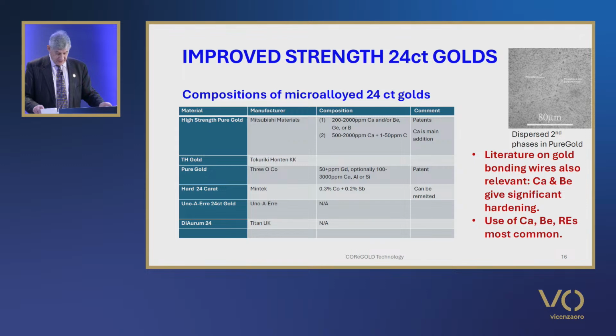The 3O company patent indicates that the pure gold material contains 99.7% gold plus 50 or more parts per million of gadolinium and optionally 100 to 3,000 parts per million of calcium, aluminium or silicon. In a patent from Tanaka KK in Japan, an alloy for precision casting is claimed containing small amounts of hafnium and the rare earths.